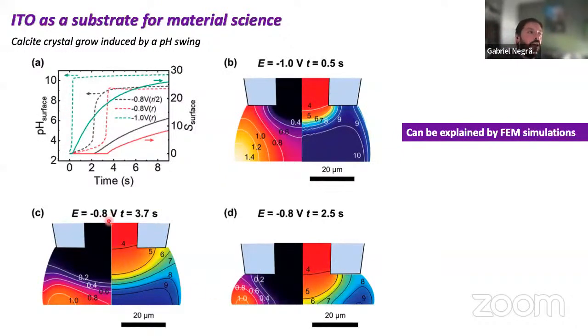But now I have an interplay of the mass transport from that pipette, which is quite high and is bringing fresh solution to the middle of this pipette. So it's buffering the effect. Even though I'm consuming protons here, I'm transporting a lot of protons, so the center of my meniscus footprint is buffered by that transport. I also have the transport of CO2 from solution to that meniscus wall, which also buffers around this region. So the first area that can get nucleation, the area that has that pH swing, is at that halo a little bit further away from the edge and further from the center.